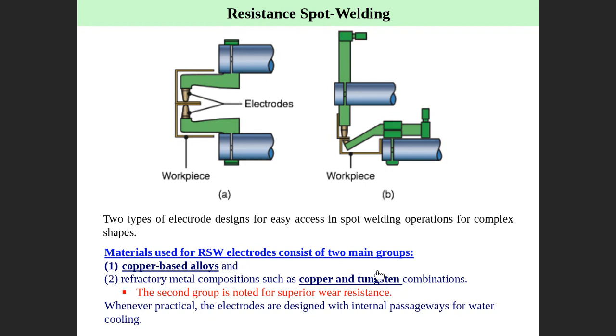Another material is copper tungsten. We add tungsten to the copper to increase the melting temperature, because tungsten is a very high melting temperature material. When you add tungsten to the copper, you get the benefits of the copper, which is excellent thermal and electrical conductivity, and you also increase the melting temperature. You know that copper melts at about 1000 degrees Celsius, but tungsten at 3500 plus. Then you get the benefit of both. Copper tungsten is an excellent material to be used as an electrode, but it is definitely more expensive than copper. Right.